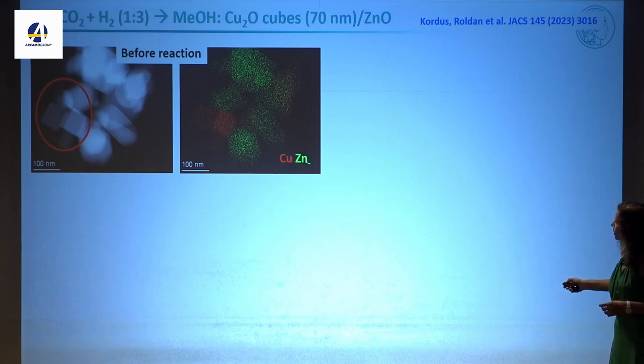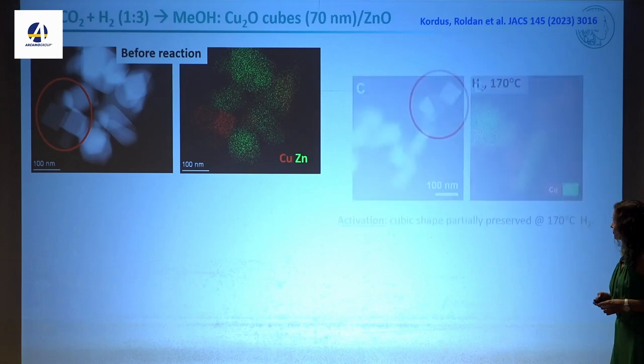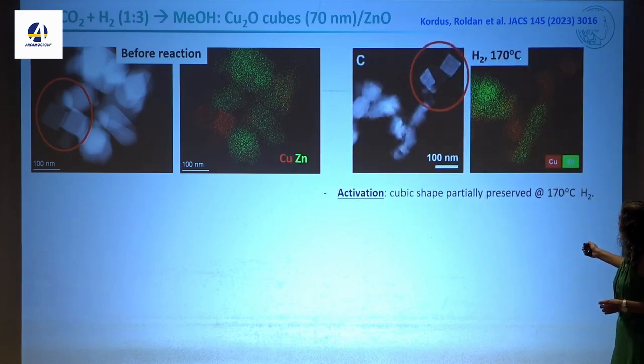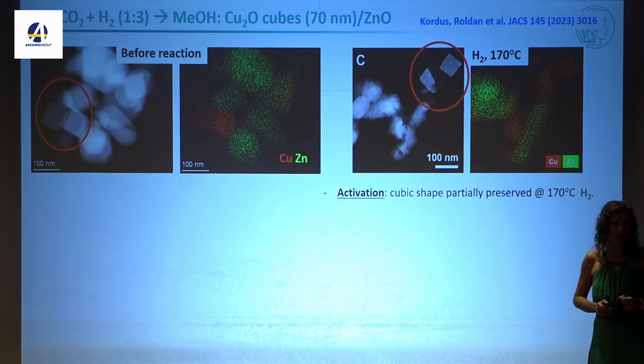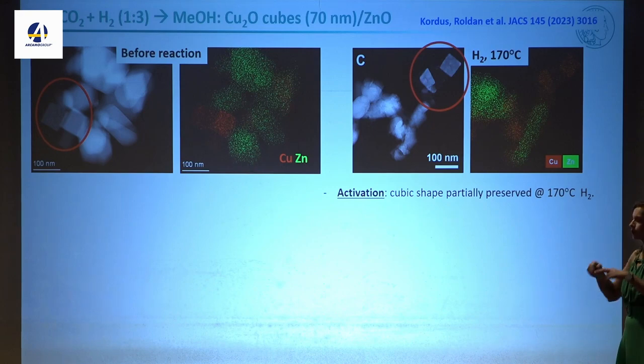You see here copper is in red and zinc is in green. And then you put it in hydrogen at 170 Celsius for, I think this was about 12 hours, and the shape of these copper oxide cubes was still there. If you go higher in the temperature, you start seeing the changes. But at least at this temperature, we can still have the copper oxide cubes with the right shape.